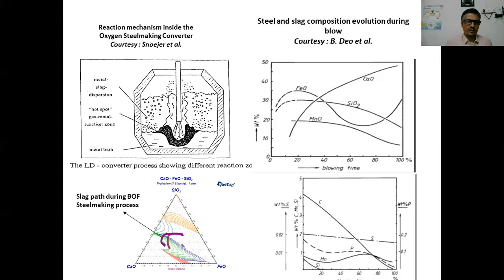Any combination of CaO and SiO2 is going to have a very high melting point, much higher than the steel making operating temperature. So unless you mix it with FeO, its melting point is not going to be reduced and it is not going to form the liquid slag. That is why, since there is a requirement of FeO, the lance height is kept higher in the initial part of the blow to promote more FeO formation. And once the FeO that has been formed in the initial part is able to dissolve the lime in enough quantity and enough volume of liquid slag has been formed, then the lance height is lowered in steps.